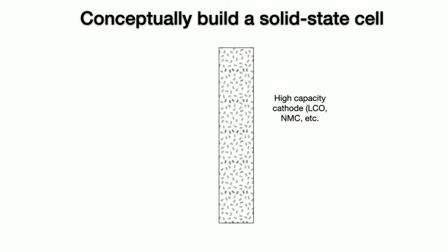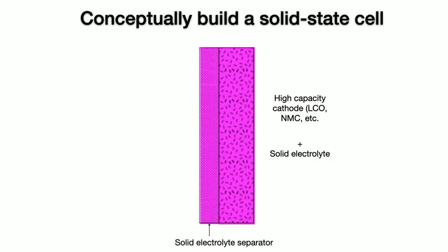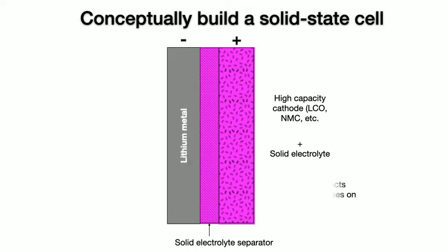We can conceptually build a solid state cell, look at what's involved in building a solid state cell. And so like any battery, there's going to be a cathode or the positive electrode. Typically, those cathodes are going to be comprised of lithium cobalt oxide, NMC, other possibilities. And then that has to have a solid electrolyte blended in with it. This is tricky. And then, of course, there's a solid electrolyte separator. It may well be the same material that's in the cathode composite. And then you introduce lithium metal.